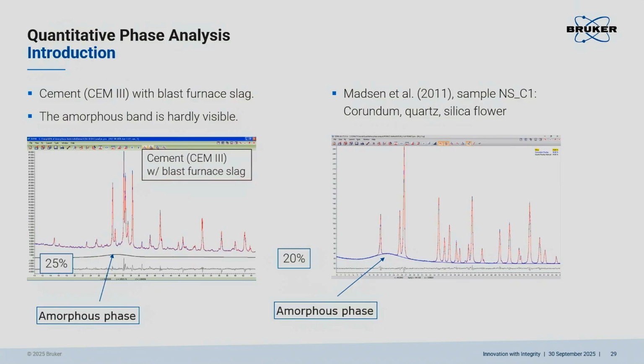Maybe that's not important for you, but I find most of the time that people are shocked if you tell them, hey, you have 25 or even more % amorphous content, and they wouldn't know. And they have always reported relative phase amounts, but not absolute phase amounts. Here, just as a comparison, a different sample from a paper in 2011, just to illustrate that about the same amount of amorphous phase can be easily seen.